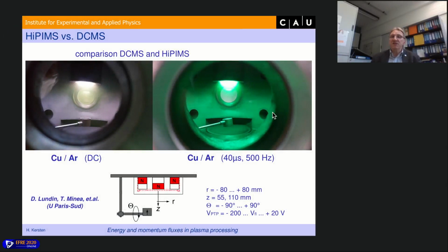You can even see it by eye in the discharge chamber. This is the magnetron, a 2-inch magnetron with a copper target in an argon discharge. On the left-hand side it is a DC discharge, and on the right-hand side a HiPIMS discharge, here at 500 hertz and 40 microsecond pulses. And you can even see it by the color.